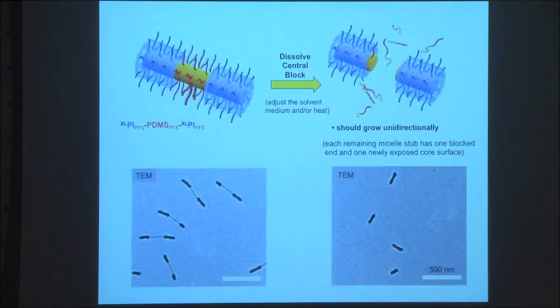The next step is to dissolve out the middle, because this should be possible to solubilize since it's not cross-linked. You don't have a cross-linked corona on the central block. And the aim is to dissolve this out, and you can do this by adjusting the solvent and also heating a little bit. And if you can remove the middle, you should generate structures which have a newly exposed face here and here, which should be active to crystallization-driven self-assembly, whereas the other ends should be blocked. So again, you can monitor this process. Here's the tri-block comicelles. You dissolved out the middle. And here we have the ends, and we're hoping that one of these ends is active and the other end is blocked.